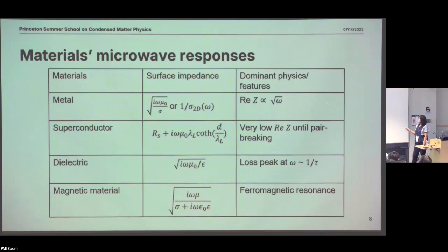And the physics were featured here. You have really low real part of the impedance, or just your loss is really small, until you have some pair breaking, where you have vortices, you have those quasi-particle excitations. And for magnetic materials, on the other hand, essentially you have this mu inside. This permeability can also be a function of frequency. And more importantly, the ferromagnetic resonances, the spin resonances, and so on, often happen also in this microwave regime.